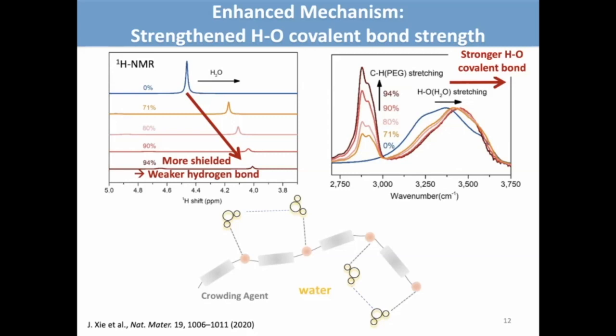So to further understand how the crowding agent changes the environment of water molecules, we use NMR and FTIR to probe, as we increase the PEG content, how does that change water's environment? So here we can see through NMR that as we increase the PEG content, the water actually becomes more shielded, which indicates a weaker hydrogen bond network around the water.